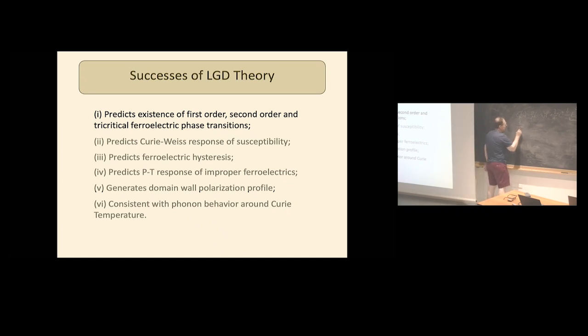Okay, let's do the normal thing. Let's search for equilibrium. So we set that equal to 0. We have A(T minus Tc)P plus BP cubed minus E, all right? Then that equals 0, so I can rearrange that, take the minus E over to the other side, or add field to both sides, and end up with a statement for the field. So this is the relationship between the field and the polarization under equilibrium.